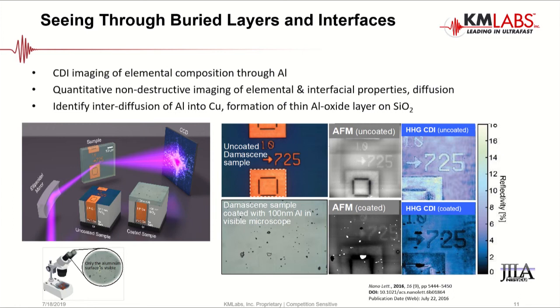So I mentioned we can, to some degree, see the subsurface and see buried features. I wanted to give this quick example looking at, again, a pattern structure that's shown in the middle of the slide here. So this numbered pattern put down on a substrate was then coated with 100 nanometers of aluminum. When you do that and then look at it in an optical microscope, of course, the pattern is completely gone. All you see is the surface of the aluminum. When you look at it with AFM, a little bit further to the right, you can see that in the uncoated case, we see this pattern pretty clearly. And even with the coated case, there's some amount of topography that is propagating its way up through that coating layer. So we still have some resolving power with AFM in this case.